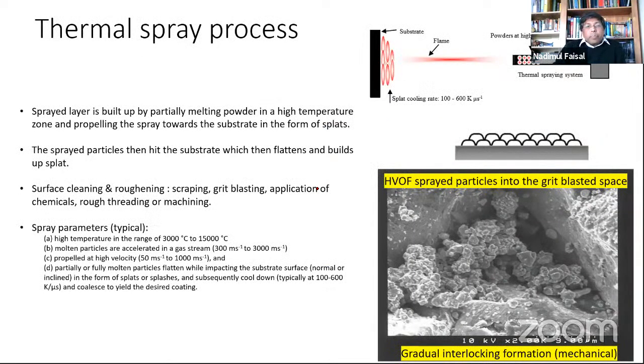Right, so in the thermal spray process, a powder particle or feedstock material is sprayed in an environment at very high velocity and temperature, which propels it through the environment, and the particle lands on the substrate. Then, layer by layer, you can build a coating. If you spray only a few particles on the substrate, you can see in the image here, it is a grit blasted surface.